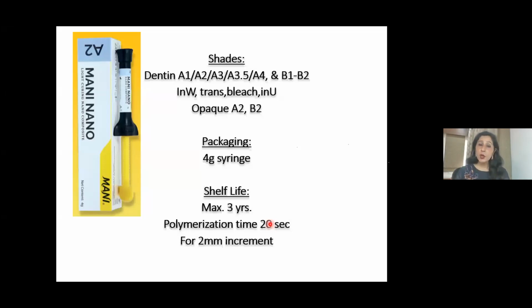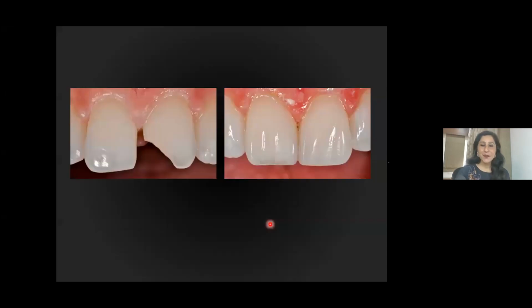The polymerization time is 20 seconds and 2 millimeter increment should be used. So 2 millimeter increments cure it for 20 seconds, whereas in micro, we have to cure it for 40 seconds. Remember the curing time which is given by your manufacturer, because if you overcure, it will not have a very hazardous effect, but if you do undercure, my dear friends, then that will lead to failure. So this is the lifelike appearance that you can get with Nano Composites, the Mani Nano.